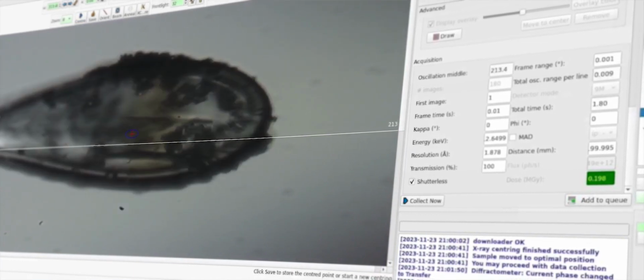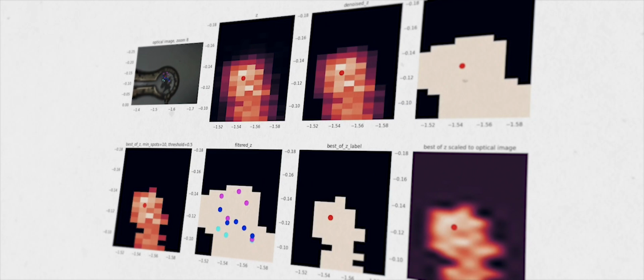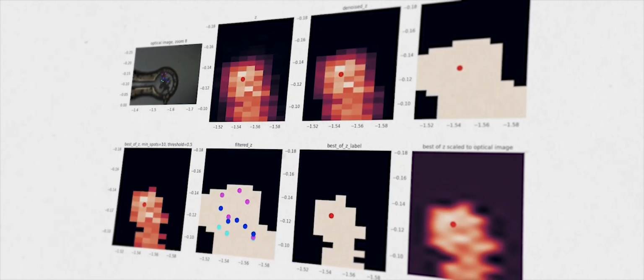X-ray centering is particularly useful for very small crystals, which can easily rotate out of the microfocused X-ray beam. This functionality scans across the sample at multiple orientations, and reconstructs the diffracting volume shape in the process, using that information then to perfectly align it with the X-ray beam. Some crystals are transparent and almost invisible in the mother liquor. Fast grid or mesh scans help to locate the crystal and also help to find the sweet spots, the parts of the crystal that diffract X-rays the best.